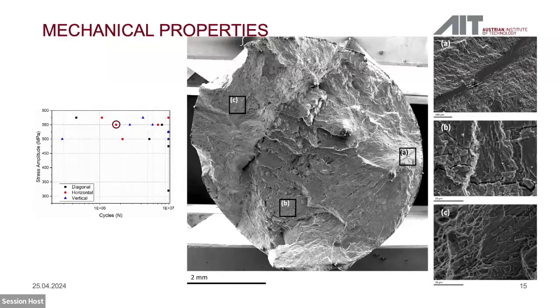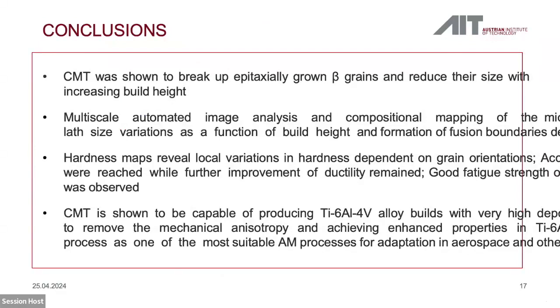Finally, some conclusions, and I will start with the lowest one. I hope I could show you that cold metal transfer is capable of producing structures from titanium alloys, titanium 6-4 in the present study. The anisotropy is weak, but should be improved. And particularly, we should be looking at fracture strain properties.